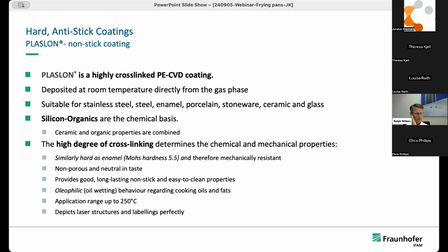It's also oleophilic, which makes it also better for cooking because the oil is spreading on the bottom of a frying pan, for example, and this gives better temperature distribution on the bottom of the frying pan. The temperature ranges up to 250 degrees Celsius, and the coating depicts also laser structures and labelings perfectly.